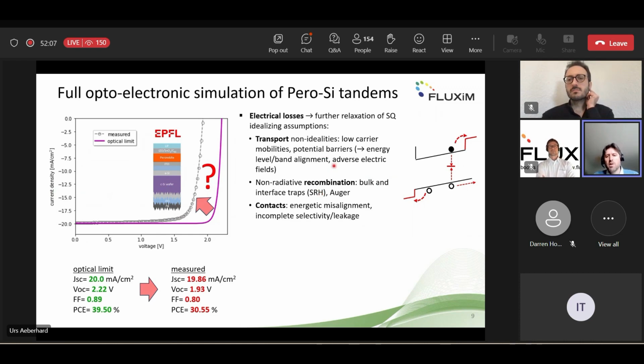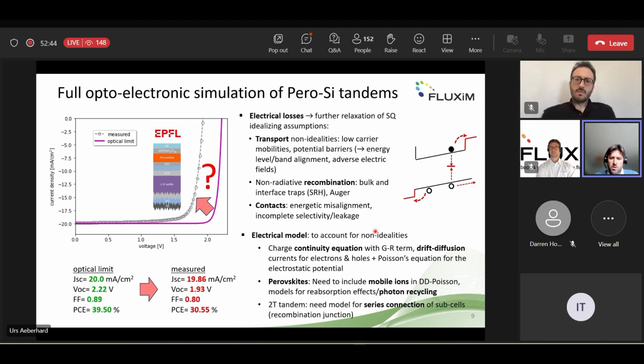So there will be transport non-idealities like low carrier mobilities or potential barriers, or even some fields that prevent efficient carrier extraction. Then also there are non-radiative recombination losses in the bulk and the interfaces. There's also Auger recombination, and then contacts can be non-ideal regarding the alignment of the energy levels or the selectivity. There might be some leakage even. And to accommodate such non-idealities, we have to combine the optical simulation with an electrical model.